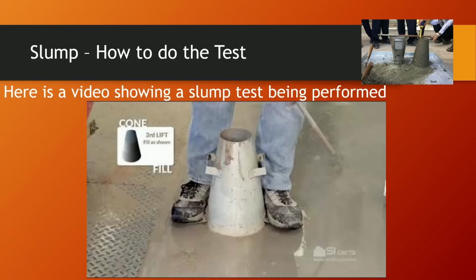If at any time the concrete falls below the lip of the mold, you'll add a representative portion of concrete back into the mold and begin rodding where you left off. With a rolling, screeding action, you'll strike off the top of the mold. The tamping rod is the only approved method for striking off the mold. Remove any excess concrete.